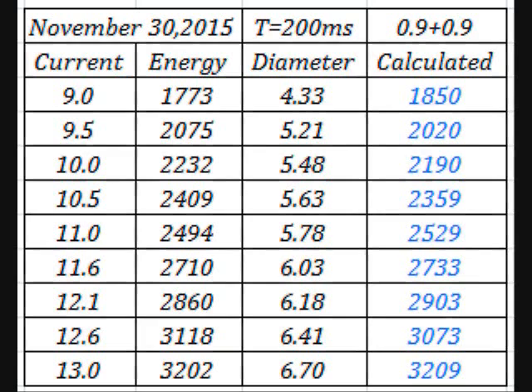This is a plot of current versus the energy with the time set at 200 milliseconds constant. This is the current in kiloampere. This is measured energy, average per coupon of 3 welds. This is the measured average of the nugget size per coupon. And this is generated by a formula. This formula is found by using the Excel trendline option, and we can see this is pretty close.